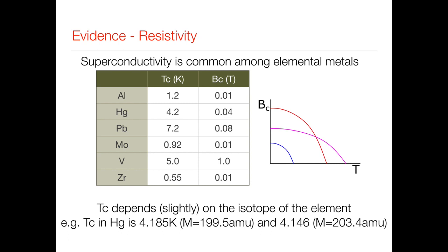The first three do correlate, but then we have something like vanadium, which has a lower TC than lead, but a much higher critical field. So this is the key thing, that whatever's going on here must be pretty ubiquitous.